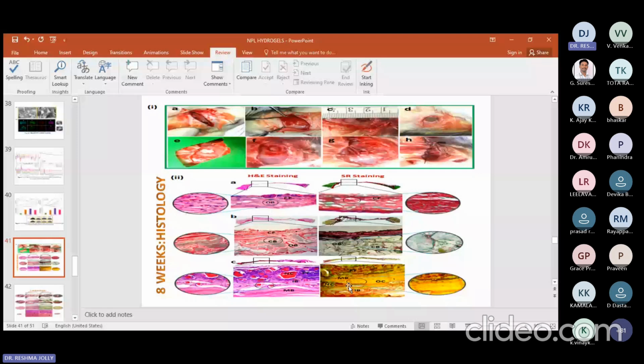Okay, so after 8 weeks of putting our material, we got the mature bone visible. And in case of commercially available Cerabone, this is Cerabone particles which can be zoomed here. So these particles are present even after 8 weeks. It means that Cerabone is also working like our material, but the advantage with our material is that it is getting degraded after 8 weeks, as we have already seen in the biodegradation studies, right?